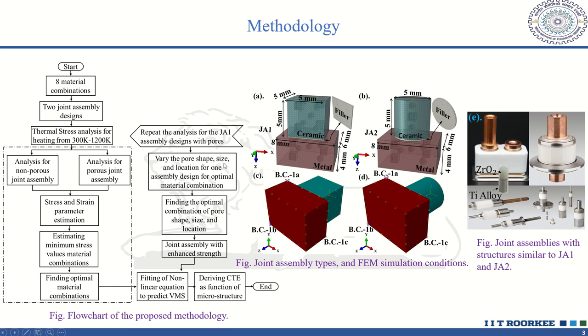Then the analysis is repeated for different pore content, that is, pore shape, size, and location in the braze interlayer of the joint assembly are varied, and the effect of different pore content is estimated. Then the optimal combination of pore shape, size, and location are derived, and then an empirical non-linear equation to predict VMS and CTE as a function of microstructure parameters are derived.